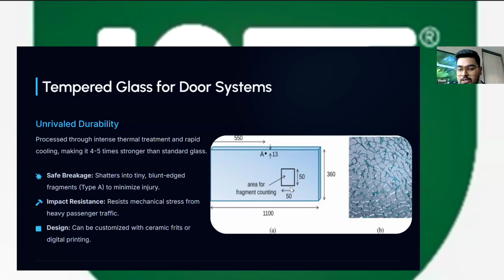After breaking the glass, we put a small box of 50 mm by 50 mm onto the glass, and the particles are counted inside the box. If the particles are less than 40, then the glass is a fail. Even if the particles are more than 90, then also it is a fail. The particle count should always come between 40 and 90, and this is also a point which should be stated in the test certificate which you ask from your vendor.